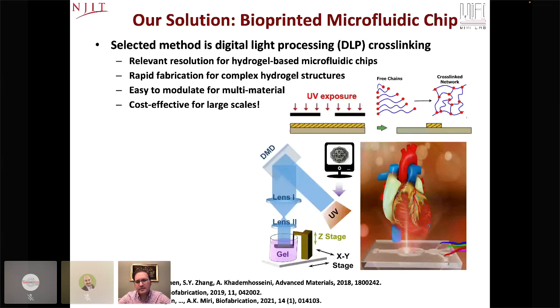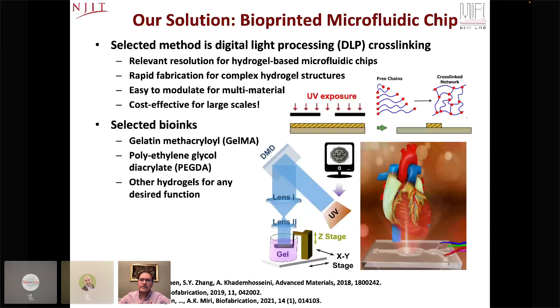Again, you can see in this slide, when you have a simple material and you expose it to light, the free radicals from your cross-linking agent attach to the acrylate sites or any photo-responsive sites in the material, and then they start to bond together. By bonding together, they cross-link or solidify. When you have a solidified phase, it means that you're going from a liquid or liquid-ish phase to a solid phase, so that you have a 3D structure.